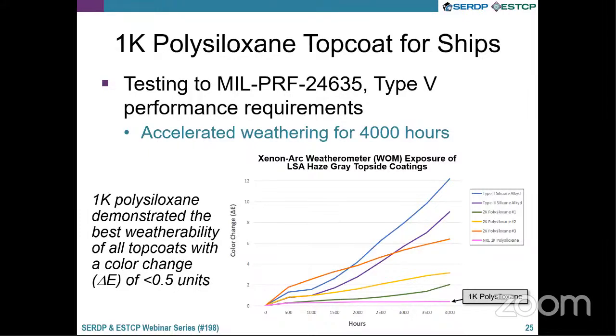You can see here the polysiloxane at 4,000 hours still had a color change of only about 0.5, whereas the best next performer was a 2-component polysiloxane, which did fairly well at a delta E of 2 at 4,000, but many of the other coatings, even at 2,000 hours, had already had delta E changes of a couple digits, which for some of them, specifically the silicone alkyds, you can really see that color change away from a gray color to a white or other sort of colors.